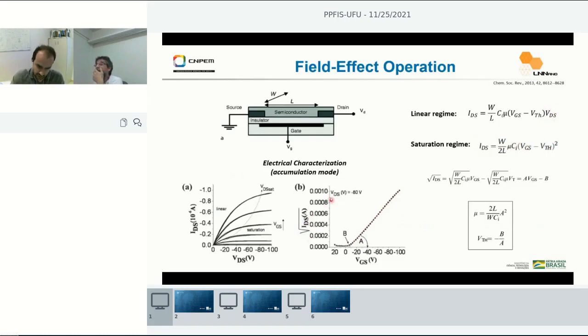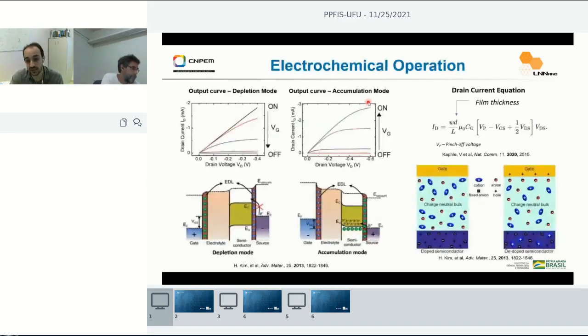You can calculate the square root of the current and plot it versus your gate voltage, where the transistor shows an off state, and then it switches on, so the current increases. The intercept of this current with the x-axis can be used to determine a parameter called threshold voltage, which is the voltage when the transistor switches on, and the slope can be used to calculate the field effect carrier mobility. So when the transistor operates in field effect mode, you can use the same physics to characterize the device, even if you are using a solution-gated transistor.